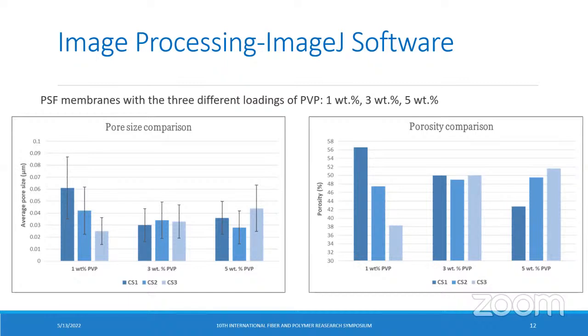But I see your point, because I have read in the literature that as we increase the concentration or loading of PVP, we should expect that the porosity and the pore size will be larger, not with the 1 weight %. I see your point. But in our case, this is the conclusion we came up with. We selected 3 different random samples, and we repeated that 3 times. So a total of 9 samples, and they all gave us the same results. Okay, thank you, Rima. Thank you very much.